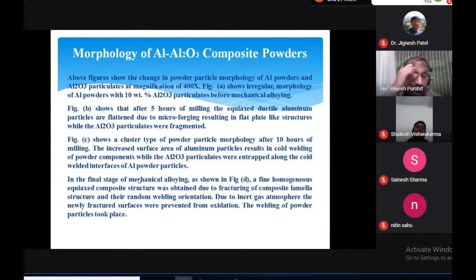Aluminum has a high tendency of oxidation, so we have to supply an inert atmosphere, that is argon or nitrogen. The welding of the powder particles took place, so cold welding takes place. Because of that, the particles, basically aluminum and oxide, get mixed together, and an alloy is formed by mechanical means.